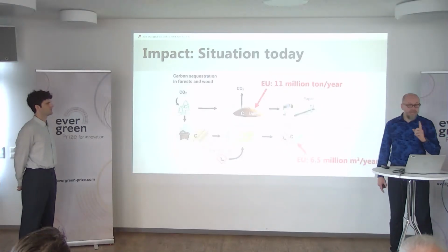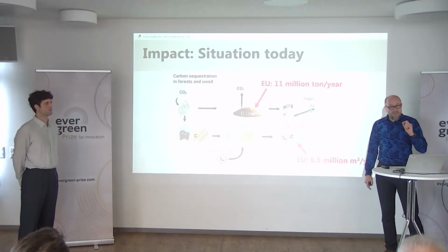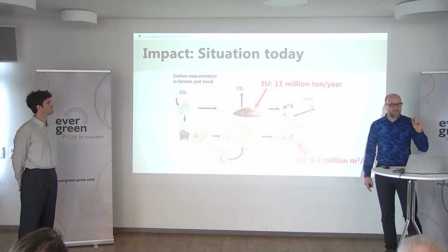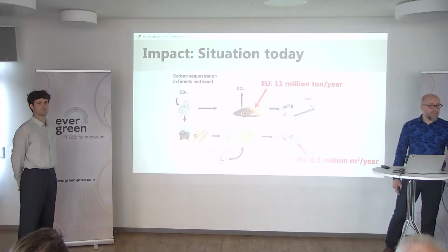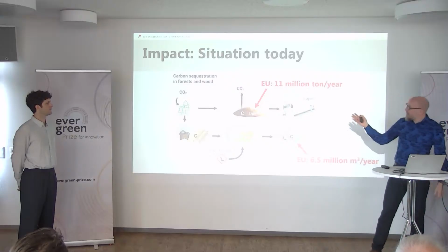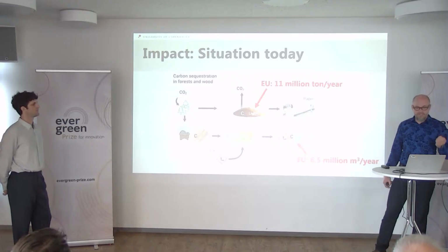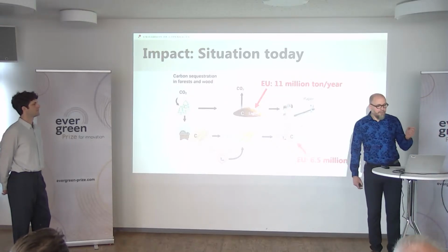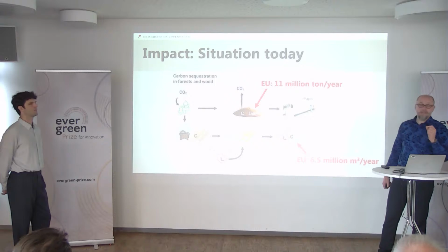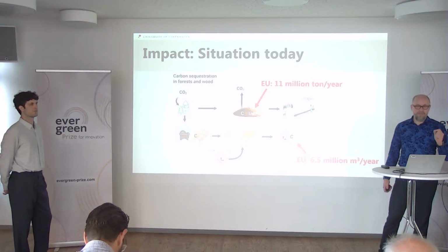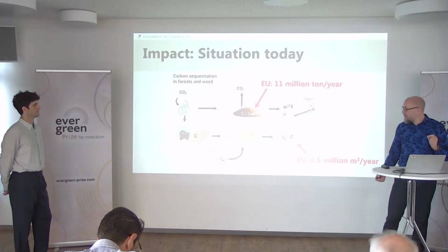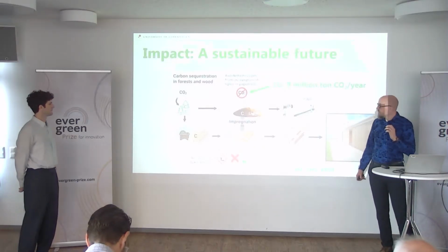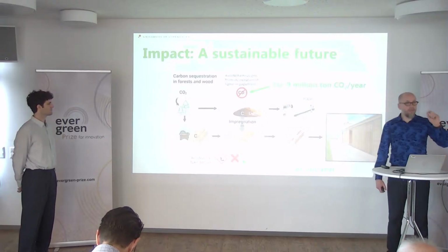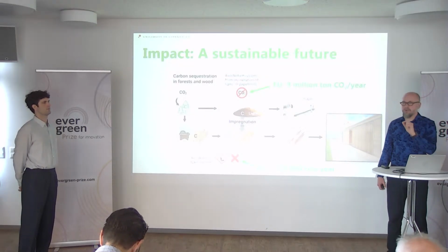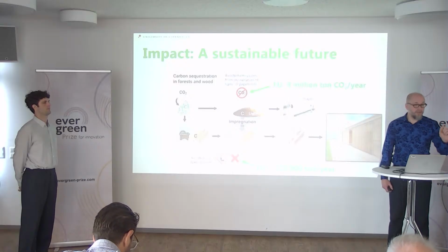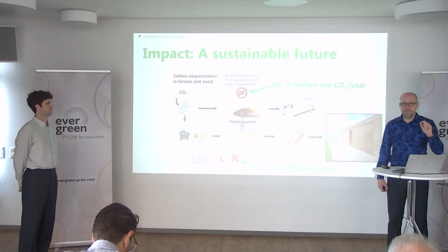Because the situation today in Europe is that the paper industry produces 11 million tons of lignin every year that's incinerated in the paper mills, whereby the carbon from the lignin is released to the atmosphere as CO2. At the same time, in Europe, we're producing 6.5 million cubic meters of biocide impregnated wood every year. And we would like to change that. So with hyperlignification, if we use 15% of the available lignin in Europe every year, 15%, we can replace all biocide treated wood in Europe.